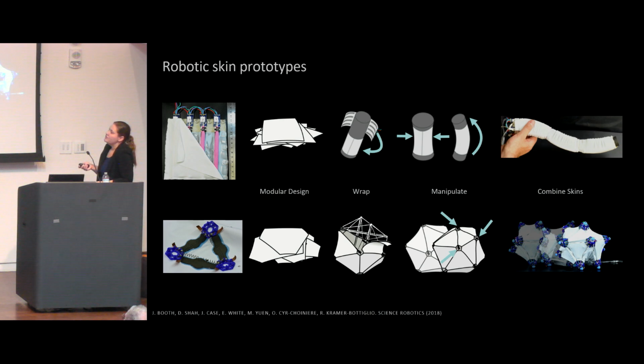So here we use a triangulation of components, which is lendable to compound curvatures. So we can get away from single curvatures like these cylinders of foam. We can wrap the skins around things that look more like spheres. So in this case, we use a 6-bar tensegrity. This is not a sphere, but kind of a ball-like shape in a tensegrity form. And we attach 20 of these skins to the outside, and we're able to take a completely inert tensegrity structure and control it, do punctuated rolling locomotion from the surface.